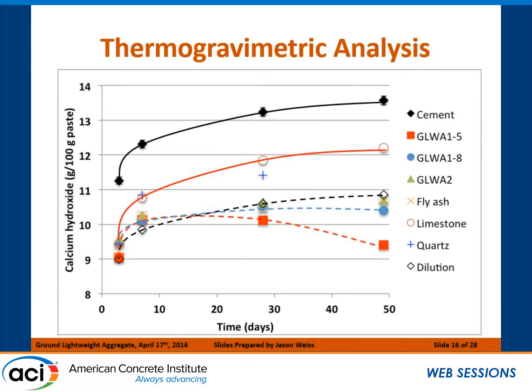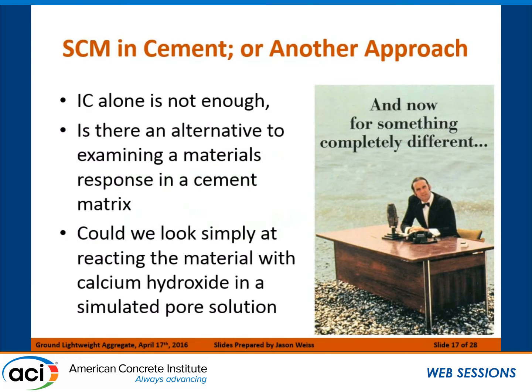So instead of continuing on this increased trajectory, we now have the effect of dilution, which slides this down, but even further, this gets slid down by the overall pozzolanic reaction. And trying to separate these curves out can become really tricky, especially when you're trying to figure out how pozzolanic a particular source is. And I'll show you an application at the end where not only how pozzolanic the material is, but how much calcium hydroxide it consumes is very, very important when it comes to some durability-related problems. So what I would like to make an argument here is that isothermal calorimetry on its own isn't enough, and there's some alternatives that we can really look at.